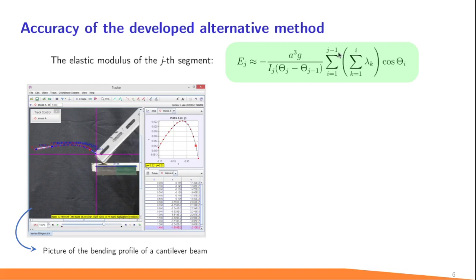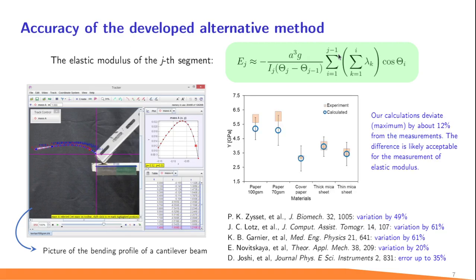And to further confirm the estimation results, we directly measured the elastic modulus of the samples with tensile tests, and our estimation deviates by about 12% from the measurement. This difference is likely acceptable since the measurement of the elastic modulus is generally not precise.